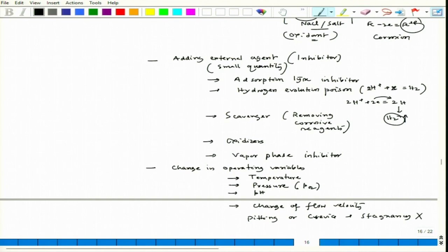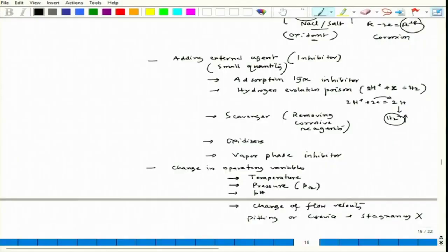it was kept idle for 1.5 months during the pandemic period, and that led to a serious level of pitting, and some of the blades inside the tank, which were actually pumps, got into a very bad shape, and then the whole tank was redesigned and recommissioned. Okay. So, we will talk about that. So, the stagnancy is bad for pitting and crevice. If we have a little flow, it actually helps. So, we will talk about change in operating variables.